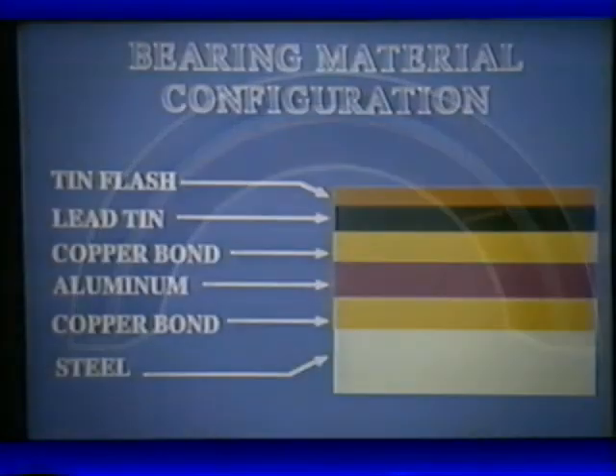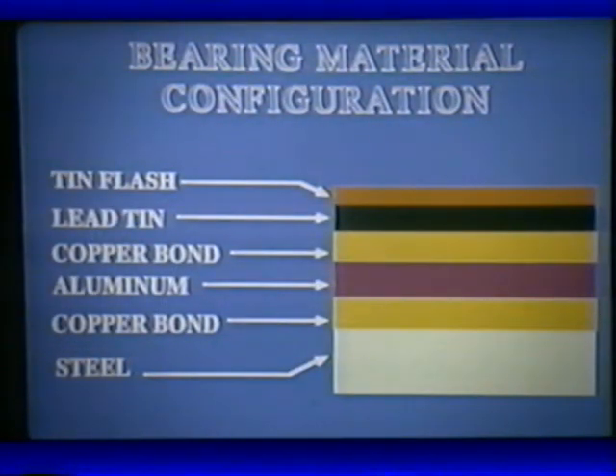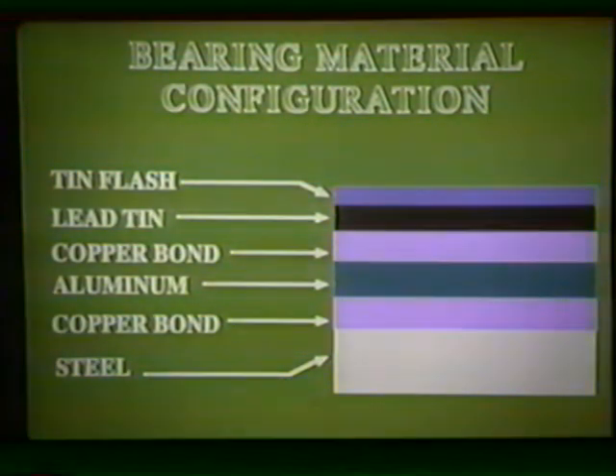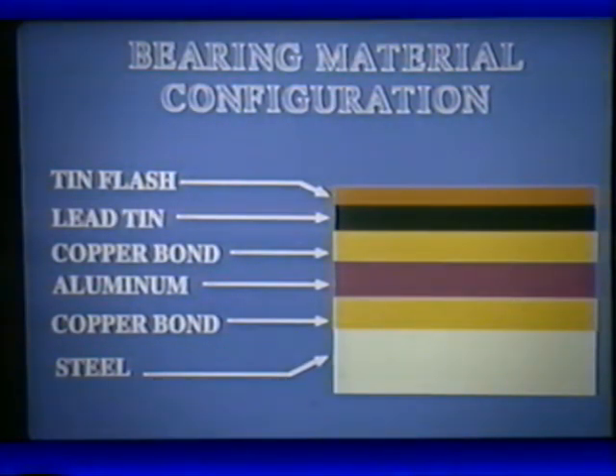The tri-metal bearings in current use combine the best properties of all three metals. The steel backing gives the composite bearing sufficient rigidity, while the lead-tin overlay exhibits superior embeddability and lubrication. A flash plating of tin is added to the overlay to inhibit corrosion, which can take place during storage or as a result of accumulated crankcase gases. The lead, tin, and steel are bonded to an aluminum center, which is hard enough for extreme service and resists acids which build up in the oil. A copper bonding material is normally used to assure that the layers are adequately bonded.